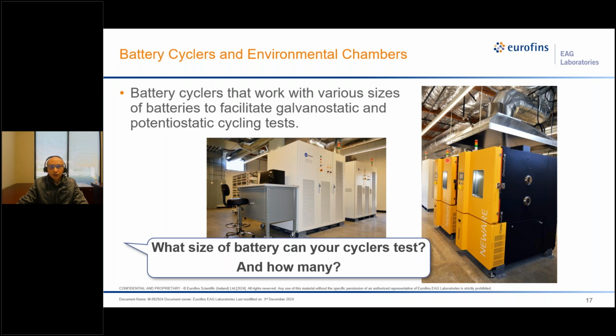And we also have 2 environmental chambers, which have full humidity control from 0 to 100%, and the temperature range is from minus 40 degrees C to 150 degrees C. So we can do accelerated battery cycling tests in our lab. Also, we can control the current or control the potential during the cycling test, both modes.